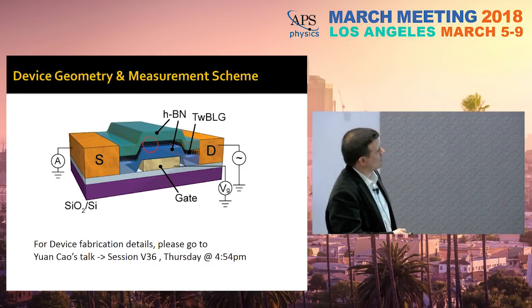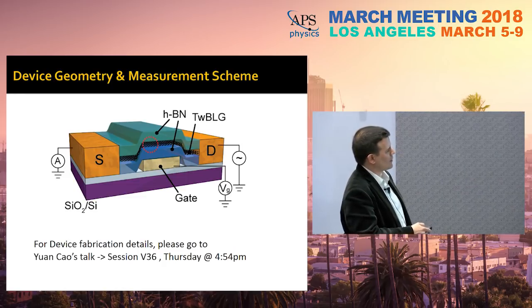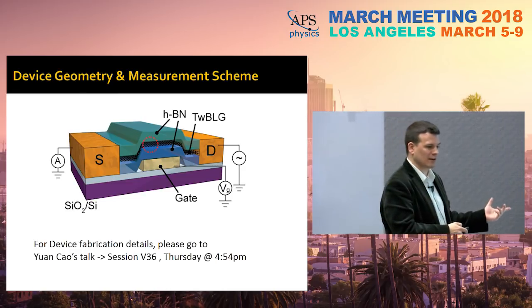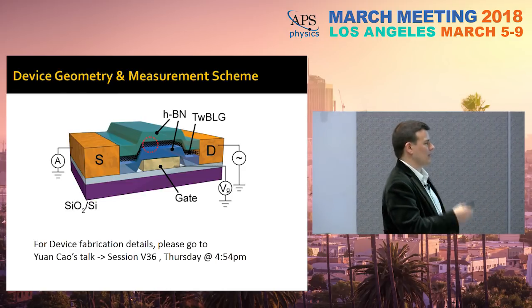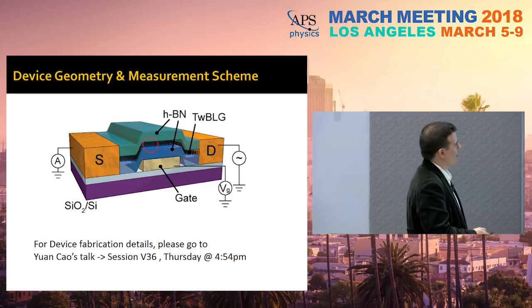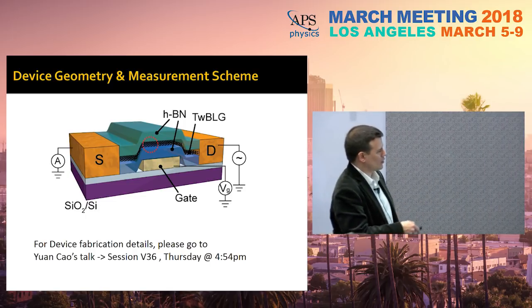So the devices look like this. We have twisted bilayer graphene encapsulated in hexagonal boron nitride. We have a bottom gate. We have source and drain contacts so that we can apply voltage and measure the current. With this gate electrode, we can control electrostatically the charge density in our system. And if you want more device fabrication details, you can go to Yuan's session.